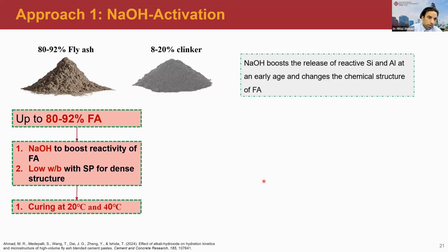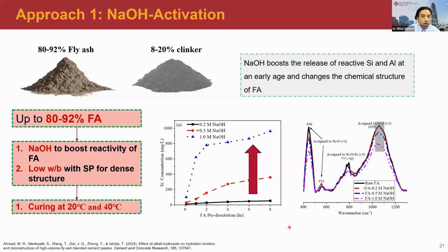The water to binder ratio is extremely important. If we use a high water to binder ratio, after evaporation it can lead to a porous structure. And I adopted two curing techniques: one is curing at 20 degrees, the other was curing at 40 degrees. What we observed is some very technical results, done by ICP. We pre-dissolved the fly ash in the sodium hydroxide before mixing with the cement.